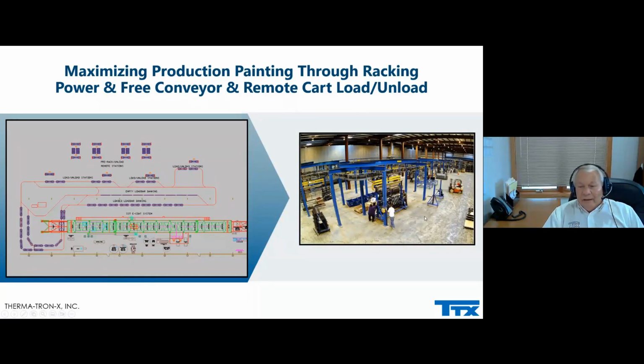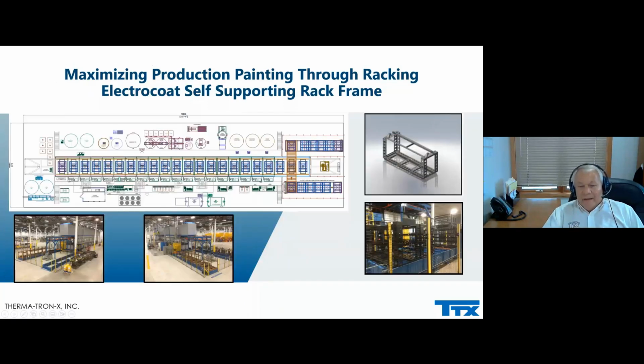Another method is the power and free, where you have stationary areas where you can actually load free rails or remote areas. This is good for captive shops or not captive shops that are custom coaters. They can have different cells for loading the highest rate. Remember, a custom coater wants to load that rack up as much as he can. And here you see that even in E-coat, they can do the rack bunching across there. And of course, these can also be done with powered rail sections or free rail sections, but you have a support system accordingly. So when you look at the back side of this, it's not such a bad way to go with self-supporting racks. And we designed the system so that we minimize the amount of drag out through the chemical stages and paint stages.